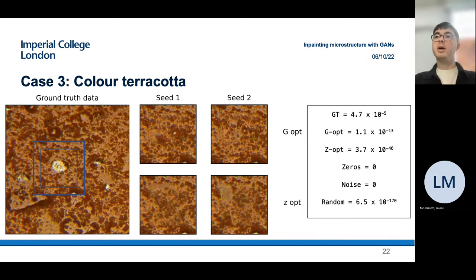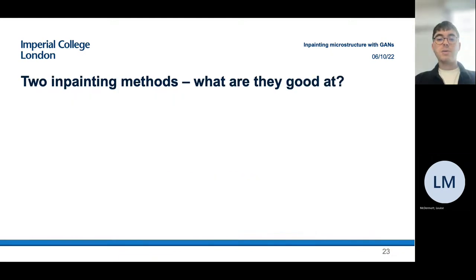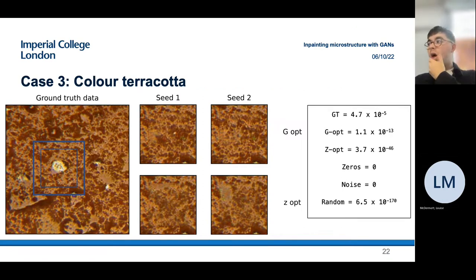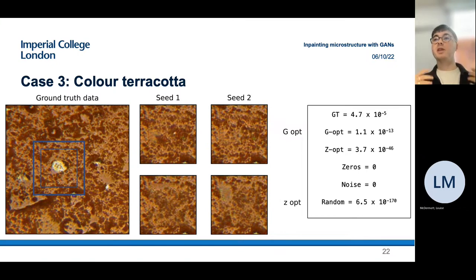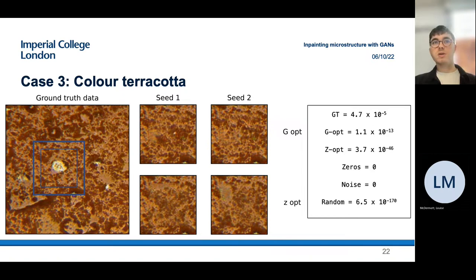In summary: for segmented n-phase materials both methods are indistinguishable from ground truth, but for grayscale and color they perform worse and are distinguishable. With seed optimization on harder problems, you start to see unrealistic blurry features around the border. This happens because during post-training seed optimization, the seed moves into regions of latent space that were rarely sampled during training, so the generator doesn't know what to do and produces unrealistic features.